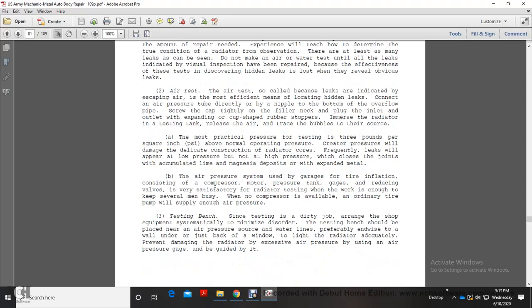Air test. The air test is so called because the leaks are indicated by escaping air. It is the most efficient means of locating hidden leaks. Connect the air pressure tube directly or by a nipple through the bottom of the overflow pipe, with a screw cap tightly on the filler neck, and plug the inlet and outlet with expanding cup-shaped rubber stoppers. Immerse the radiator in a testing tank to release the air, and trace the bubbles to the source.